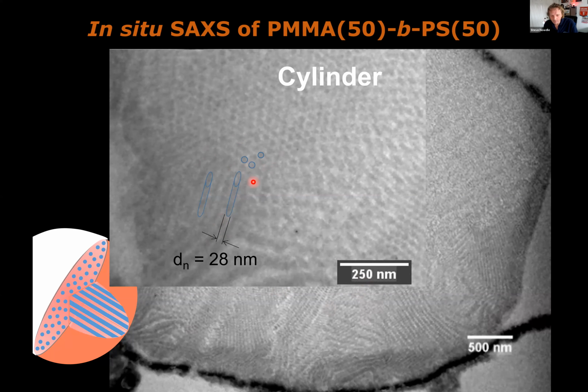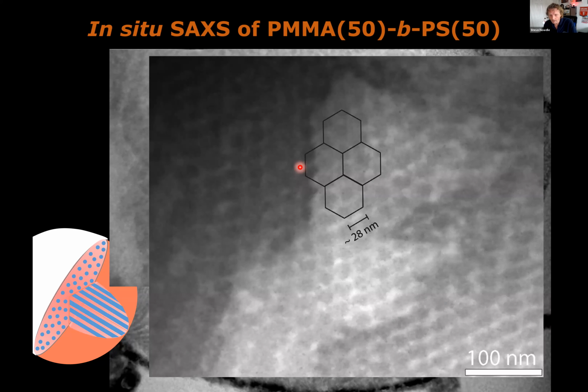So we can see we have a structure here of around about 28 nanometers, which is exactly what we had predicted that we would get. And here you can see better that these have organized into a very definite hexagonal cylindrical array. So all of this is happening inside one of those microparticles.